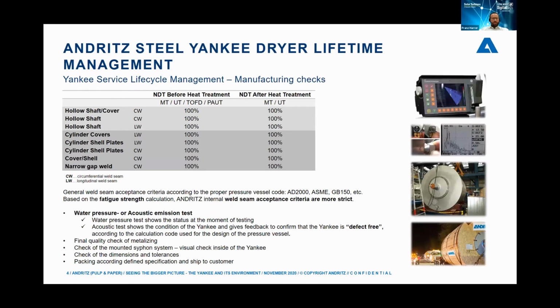As John already mentioned before, the most common tests for steel Yankees, and here the test focus is on the welding seams, are the magnetic particle test, ultrasonic test, time of flight diffraction, and phased array. And as you can see, we really recommend to do 100% testing of all the welding seams in longitudinal and circumferential direction. And we recommend to do MT and UT testing before and after the heat treatment to make sure that during the stress annealing process, no indications or cracks appear.